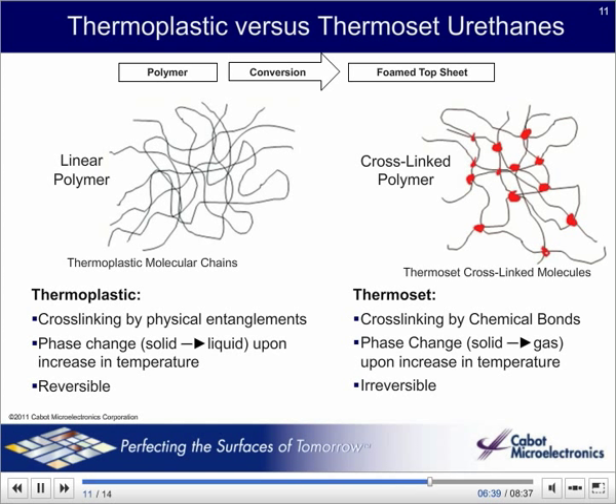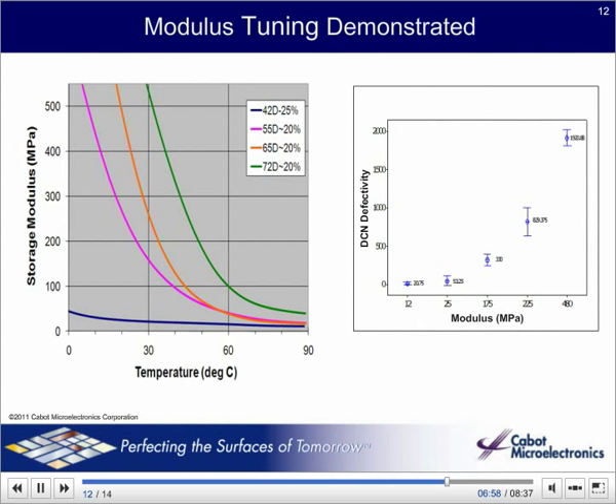During the polishing process, the interface between the wafer and the pad heats up, sometimes a lot, from room temperature all the way up to 60, 70, or 80 degrees centigrade. Our thermoplastic softens, which can be great for reducing scratches, but it also makes our rubber more difficult to condition. We can also tune the hardness or modulus of the rubber. In general, the harder the rubber, the more likely we are to see scratch defects. But hardness also improves the removal rate and uniformity, so we have to make trade-offs to optimize the process.